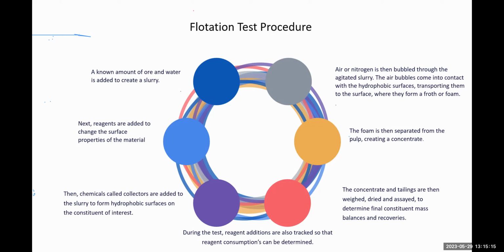Why are we adding the reagents? I told you earlier that some of these minerals do not have inherent surface properties, so you have to alter their surface chemistry. So sometimes you add reagents to it. In this case, we add some activators, sodium hydroxide, depending on whether it's spodumene or lepidolite. So once you add it, you'll be able to alter the surface chemistry of this material. Then the chemical collectors are added to the slurry to form hydrophobic surfaces on the constituents of interest.